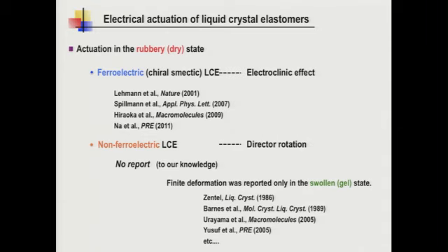In this case, we have to use the director rotation for actuations, but in the dry state, the resistance for the director rotation is very high, so we need an unrealistically high electric field. So electrical deformation has only been reported for the swollen state, the gel state.